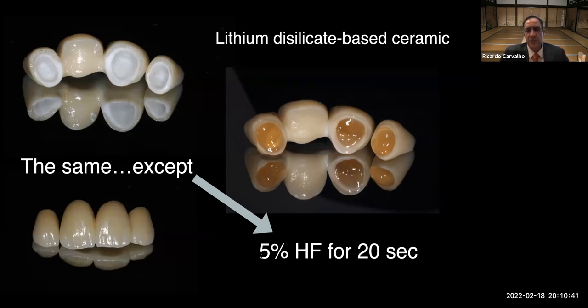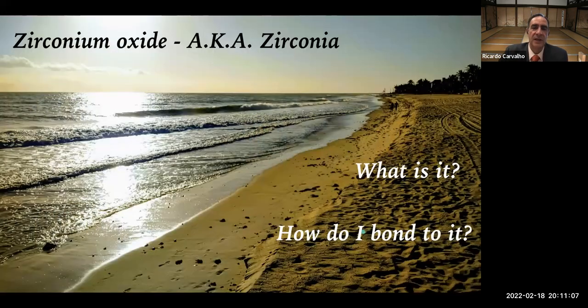And the reason why we use a lower concentration and less time is simply because lithium disilicate, although it contains silica, contains much less relative to its composition. Therefore, we don't need a stronger acid, and we don't need a lot of time to create the porosities or increase the surface energy with lithium disilicate.